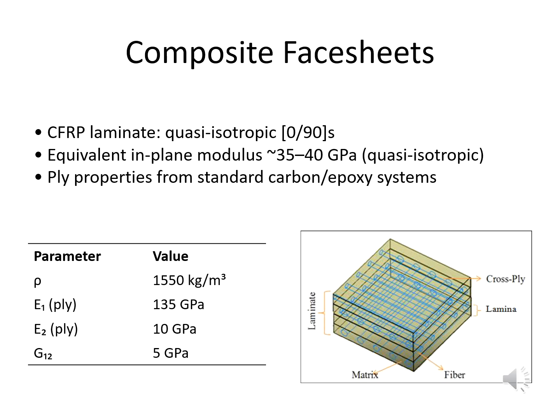The carbon fiber material properties, longitudinal modulus, transverse modulus, shear moduli, and strengths were added along with the necessary thermal properties such as thermal conductivity and specific heat. These thermal values are required to support the transient thermal analysis and ensure the composite behaves realistically when exposed to aerodynamic heating. Failure evaluation uses established criteria including Tsai-Hill, Tsai-Wu, and Hashin.